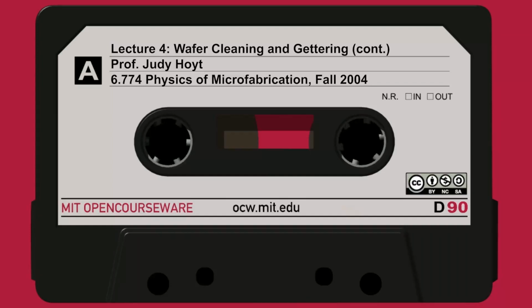Sometimes in fabs today, prior to doing the actual wet chemistry to remove the photoresist, people do a dry process, and we'll talk later in this course about dry etching. But there are ways to create reactive species in the gas phase that will also attack the resist and remove it. Oxygen plasma is often used to remove photoresist, sometimes prior to doing the wet chemical strip. So after you do this sulfuric peroxide step,